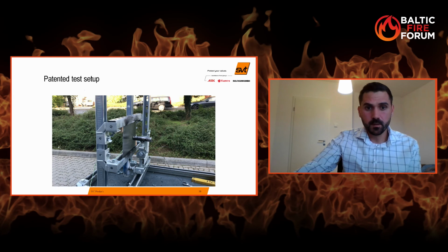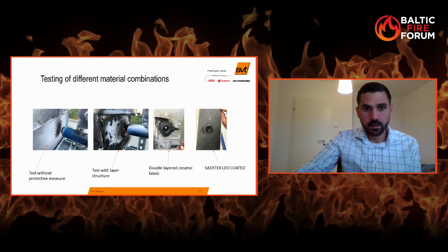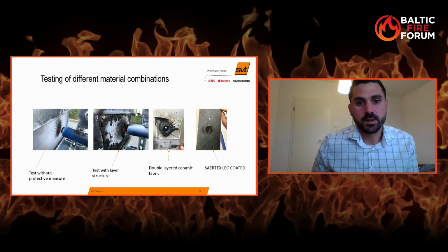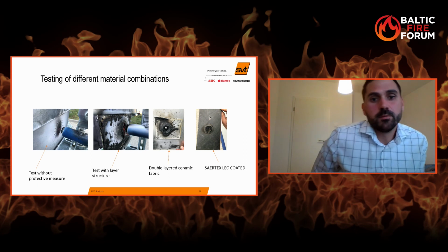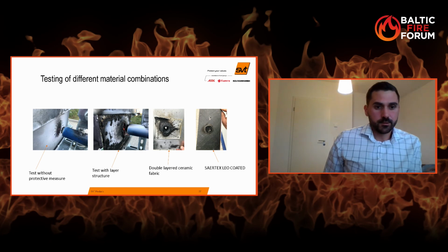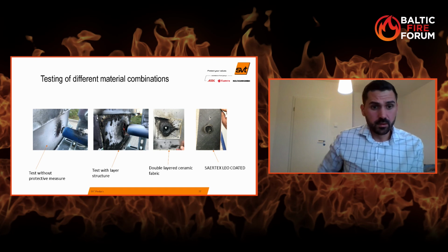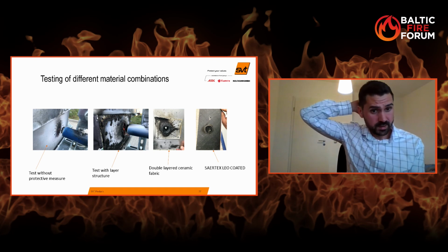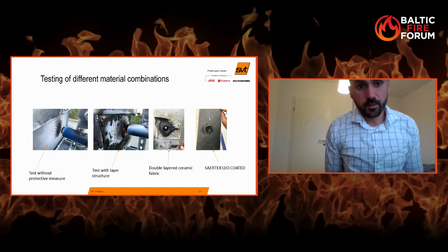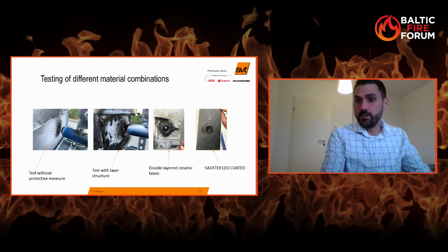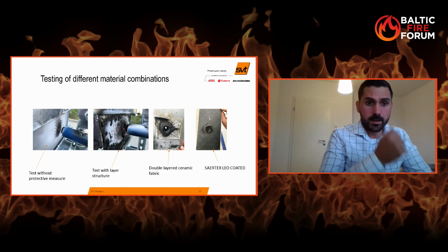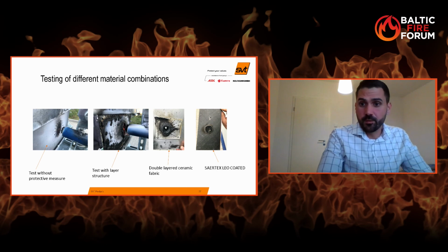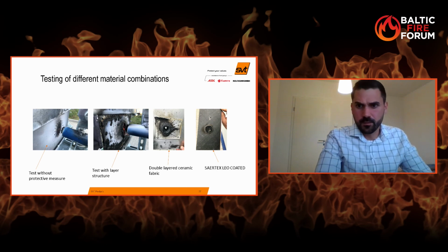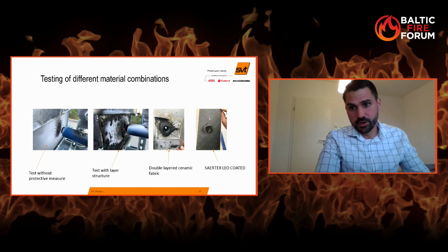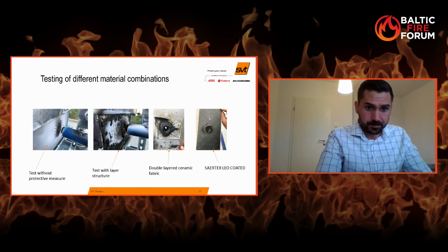Here you can see some different material combinations that we have tested. As you can see below on the left side, there is the test for just a 2 mm aluminum plate, and the jet flame goes through for about 3 or 4 seconds, I guess. Then the jet flame comes out on the other side.